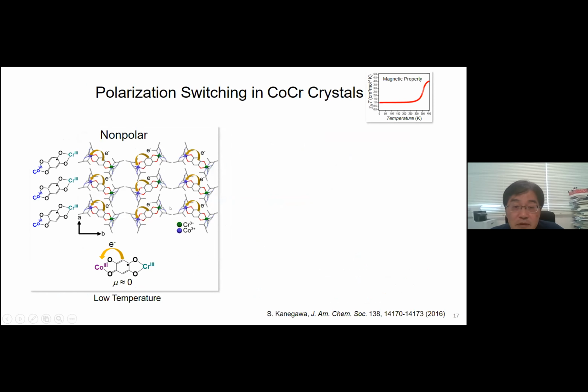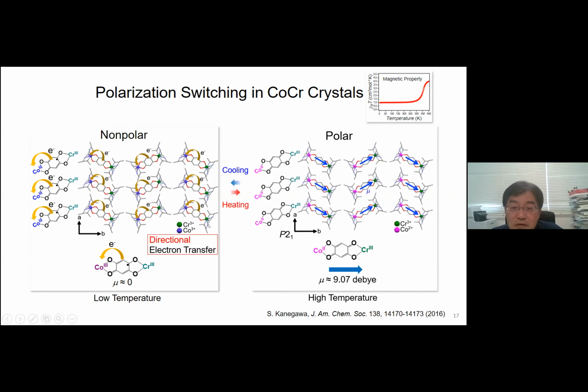And as I mentioned, these molecules are oriented in the same direction. Cobalt, chromium, cobalt, chromium, cobalt. So this electron transfer should be directional, as shown here. So this transition is directional, and a non-polar structure is transformed to a polar structure. So this means polarization switching via electron transfer is induced. And this is a new polarization switching material using electron transfer.